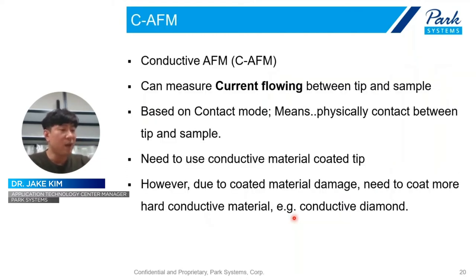Next is the conductive AFM, the CAFM. Using conductive AFM, just simply speaking, we can measure the current value, the current signal. And it is also contact mode based. So a hard conductive material coated tip is recommended, just similar to PFM.